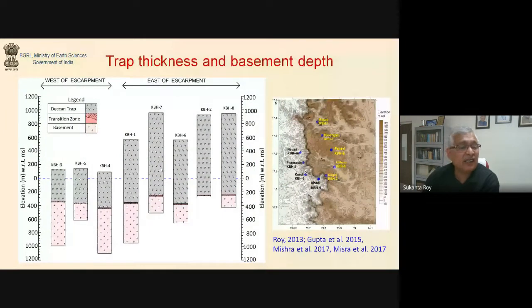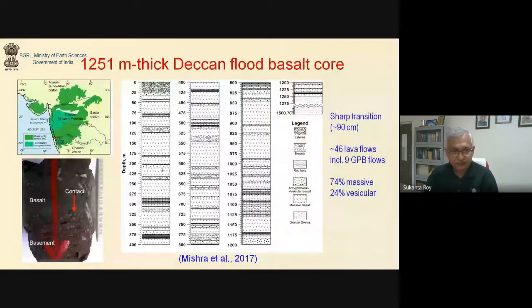So here you can see the trap thickness and the basement in all the boreholes shown here, and you can see that the depth to the granitic basement is more or less within about 100 meters. Now, in one of the boreholes, we actually recovered a 1251 meter thick Deccan basalt core, and this is, to my knowledge, the longest continuous vertical core of Deccan flood basalt from the Deccan traps. All the boreholes were vertical, so I must tell that.